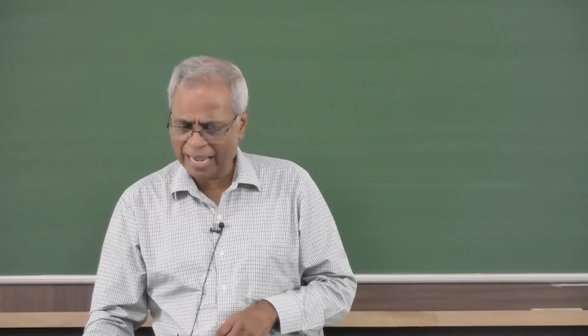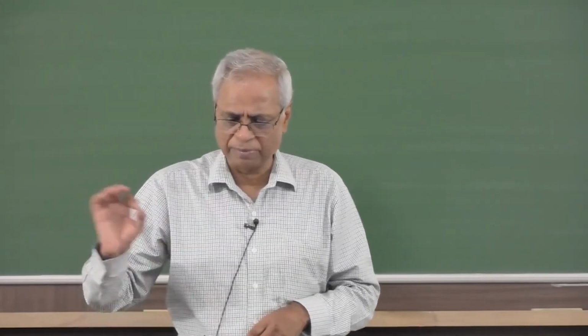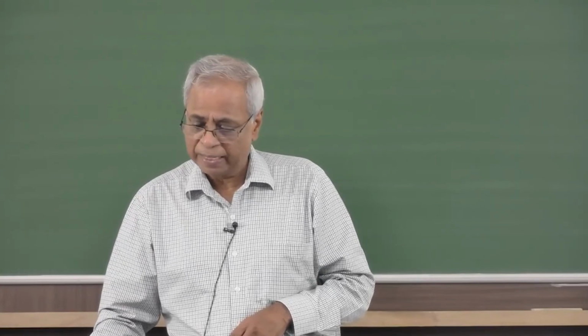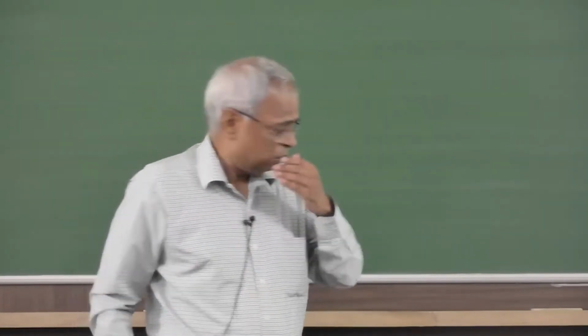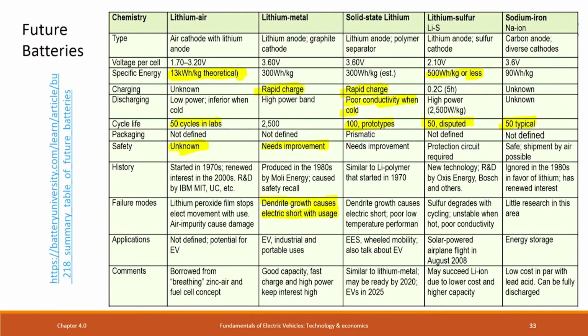Solid state lithium, again 300 watt hour per kg and possibly can go up. It also does rate, it can also charge very rapidly, 3C is no problem. It is bad in cold weather. It has very poor conductivity, it does not work at all. Cycle life in all prototypes has not exceeded 100.